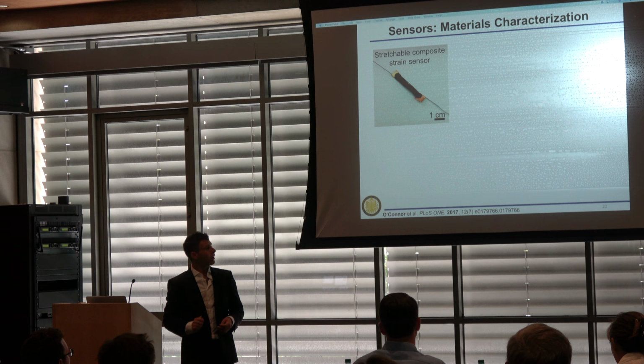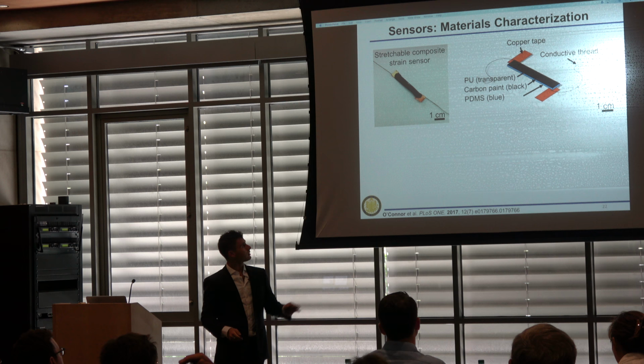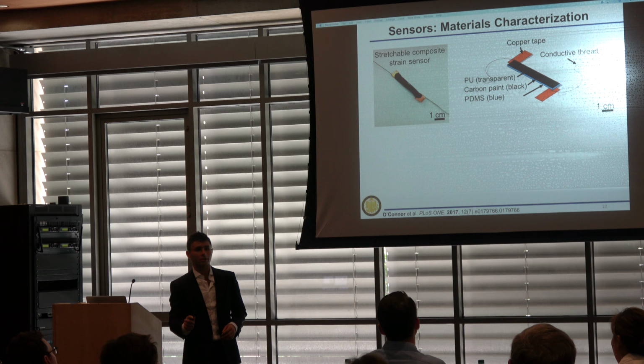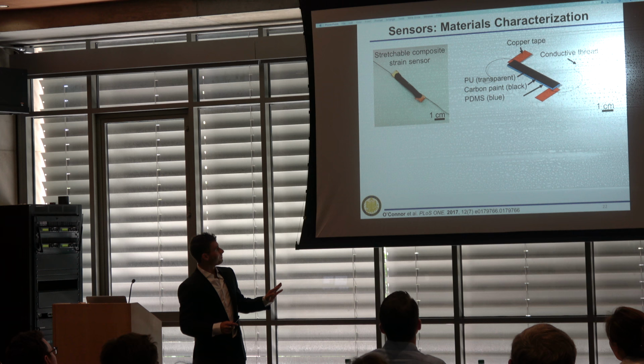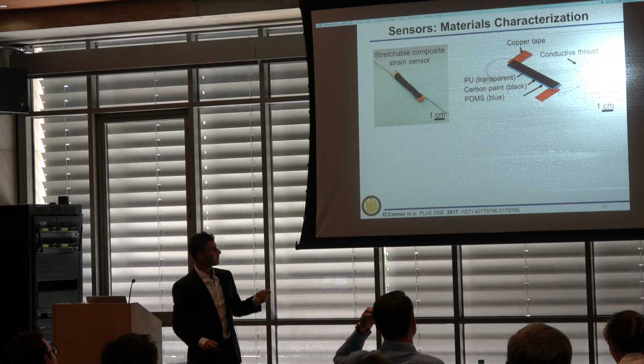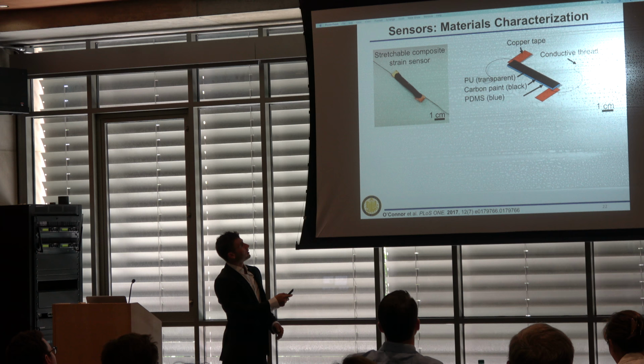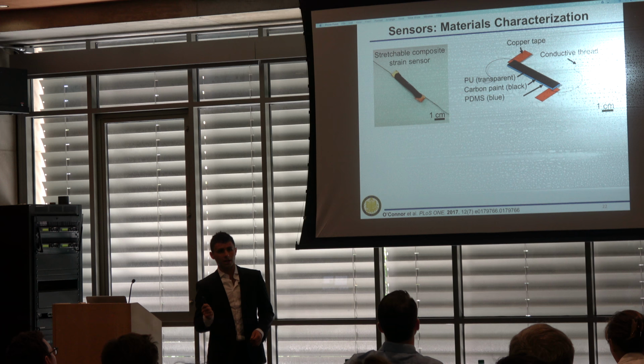Okay, so these are what our sensors look like. They're about 3 centimeters long and about 500 microns thick. They have a PDMS substrate with an electronic ink painted on them, which makes a piezo-resistive film. It's actually made out of this commercially available electronic paint that is used to ground samples in electron microscopes. Then polyurethane is used to encapsulate it, with copper tape and a conductive thread to establish electrical contact.